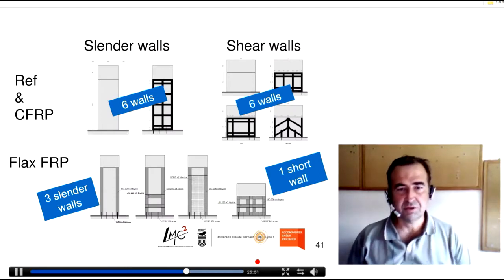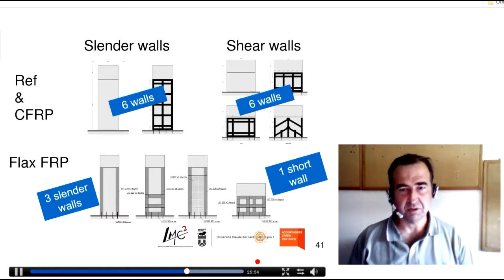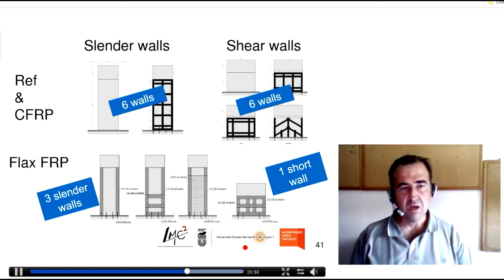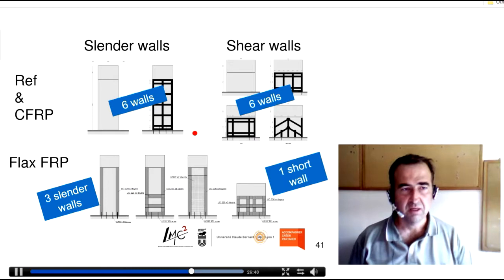Third stage of our research, and this part was done in collaboration with Enzo Martinelli at Salerno University, was to evaluate the efficiency of such flax fibers for reinforced concrete walls for seismic retrofitting. The idea was to use such kind of fibers so that we can replace carbon ones for walls that are loaded by compression and cyclic loading. So 6 walls were tested using carbon fabrics externally bonded to the concrete. Anchors were placed in order to ensure the continuity of force between the wall and the basement.